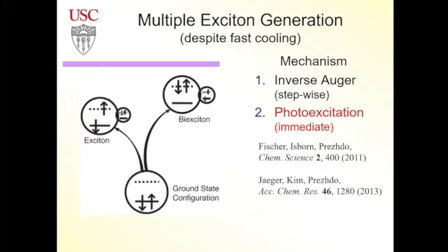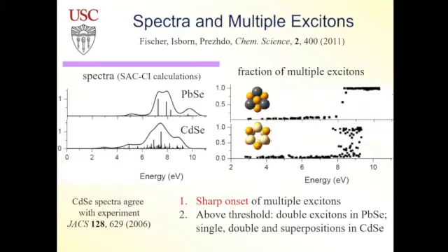But in molecules, everything is coupled very strongly, and the double excited state is very strongly coupled and mixes with the single excited state. So in small clusters, you can actually excite a biexciton that has maybe 5% mixture of single exciton. What we showed is that in small clusters, you immediately get excited states that have double excited character. The intensity of that excitation is low by optical selection rules, but still it's sufficient so that at high enough energy, you immediately generate double excited states, and maybe this way you can increase efficiencies of solar cells.